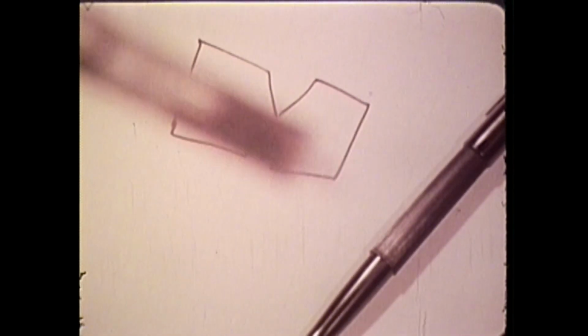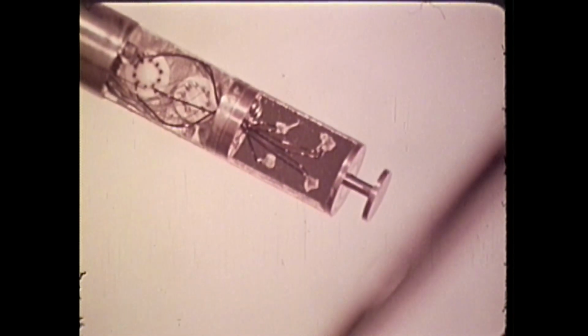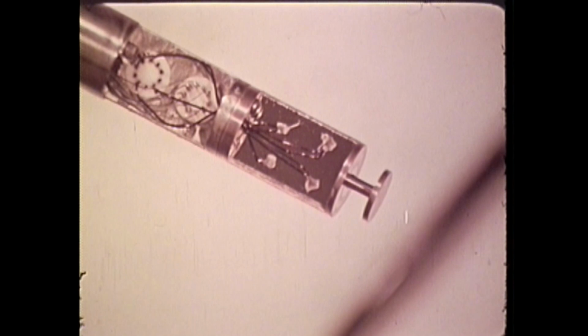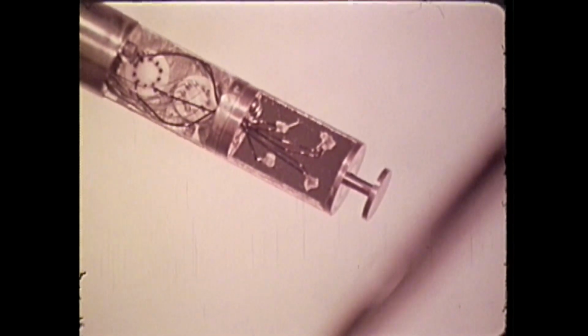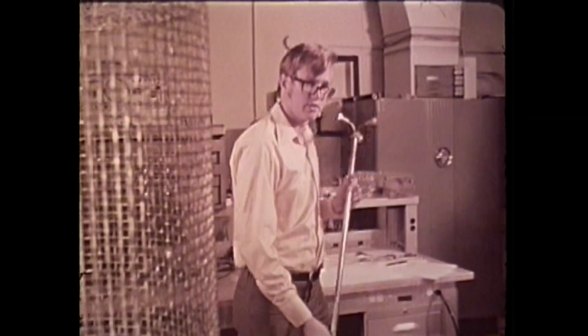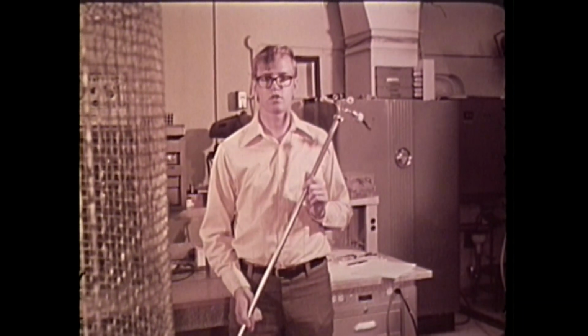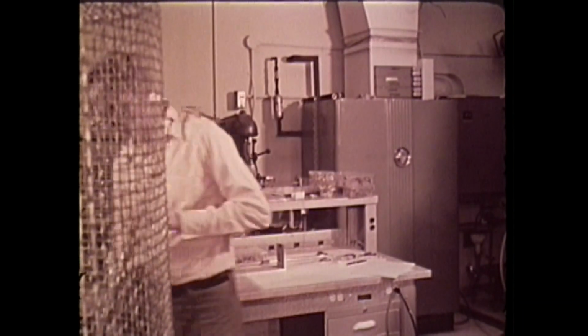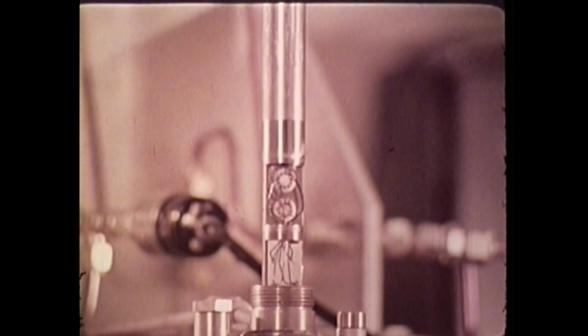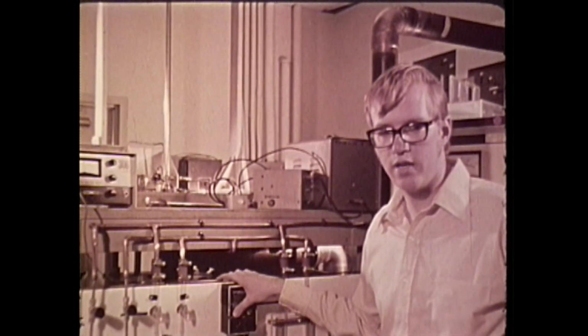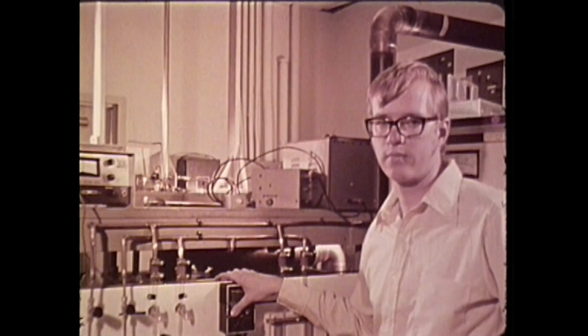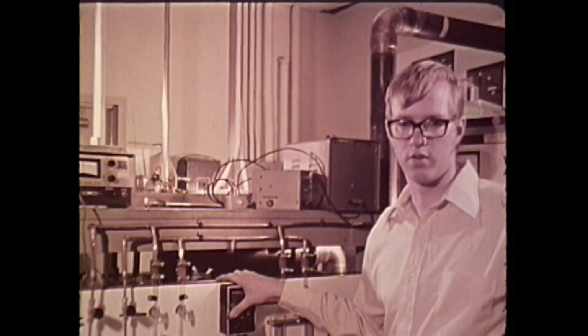We're using a scribed film technique to obtain necks even smaller than a micron. We're working with niobium nitride because it has a relatively high critical temperature, around 17 degrees Kelvin, so it doesn't need liquid helium to start its superconducting. We put our devices in a cryostat, expose them to radiation, and analyze the output. So far, it looks like we're in the ballpark.